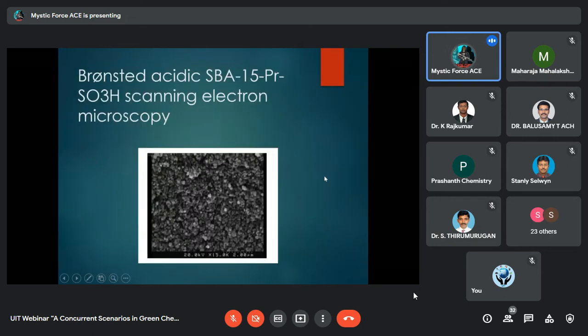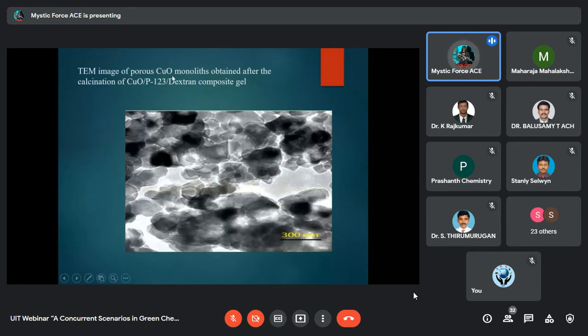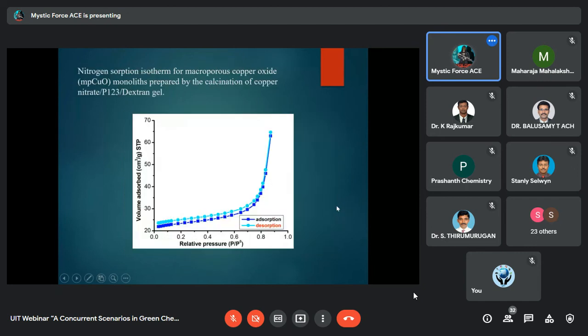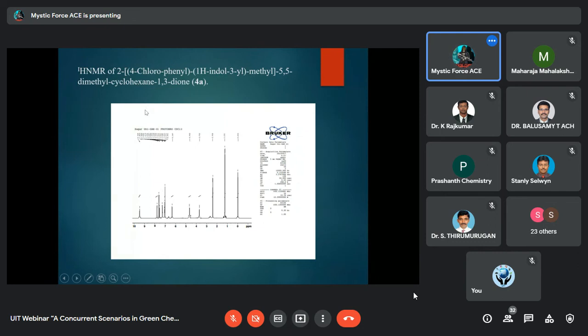This I'll skip. This is the TEM image of the porous CuO monolith which we have synthesized. This is also a beautiful TEM image of the compound. This was after calcination. This is the nitrogen sorption isotherm for macroporous cupric oxide monolith prepared by calcination of copper nitrate. Dark blue is adsorption and light blue is desorption. You can see a nice curve is there. This is the 1H NMR of our formed compounds.